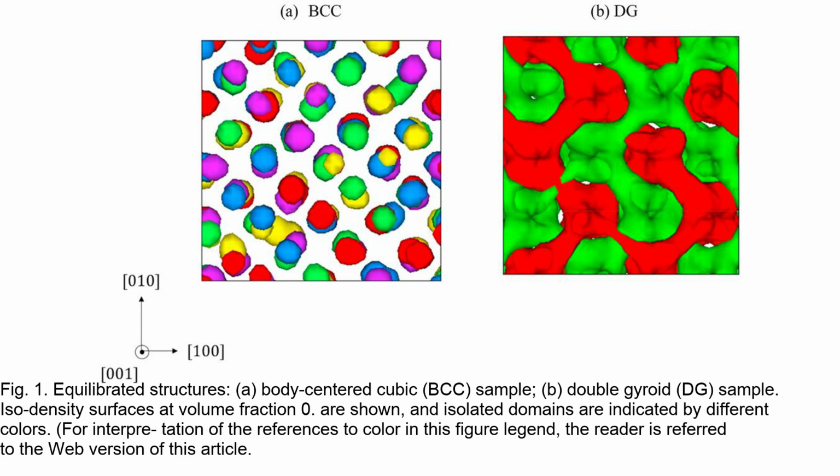Additionally, the rubber elasticity of the BCC morphology was found to be linearly dependent on the bridge fraction, while the dependency was weak in the DG morphology. This indicates that the loop configuration in the DG networks also contributes to rubber elasticity. The effect of deformation direction on the stress-strain curves was found to be insignificant for both morphologies, which is inconsistent with experimental results. This discrepancy may be attributed to the limitations of the coarse-grained bead spring model used in the simulations.